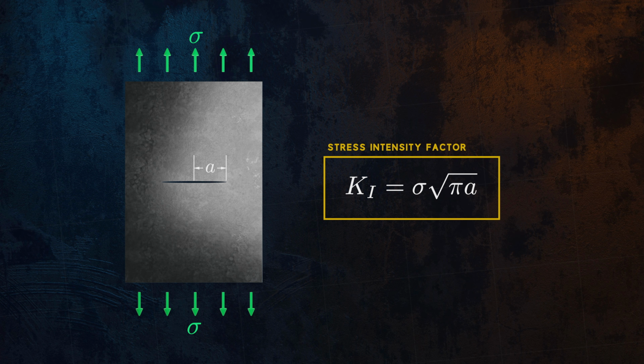For a crack in the middle of a plate, like this one, the crack size A is the distance from the center to the tip. This is half the overall length of the crack, so the total crack length is 2A. The stress intensity factor has quite unusual units, megapascal square root meters. That's because it's not an intuitive physical quantity. It's best to think of it as an engineering parameter that tells us how severe the crack tip conditions are. Larger loads or longer cracks both increase the stress intensity factor, which means more severe conditions at the crack tip, and a crack that's more likely to propagate through the material.